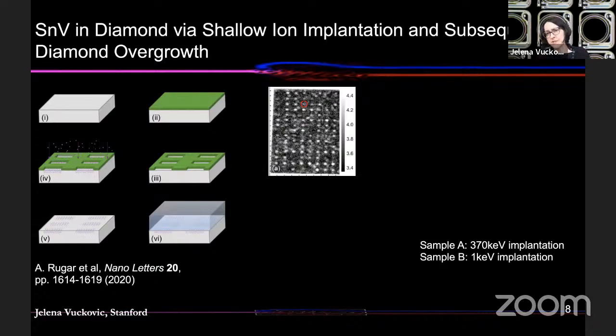And when you look at all of these experiments, in principle, they should be immune. All these inversion symmetric color centers should be immune to a static electric field. But then what happens in the experiments is that they're not exactly immune to it, because you damage the lattice. You kind of break the inversion symmetry in the process of introducing these atoms into the lattice.